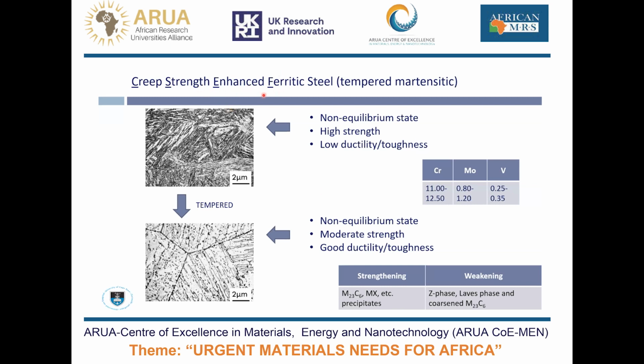So if we take the creep strength enhanced ferritic steel, which is used extensively in steam pipe in a coal-fired power plant, it's deployed in the tempered martensitic condition. And the reason for doing that, of course, is that in the fully martensitic state, it has very high strength, but very low ductility and toughness. So it's then tempered to restore some good ductility and toughness. And of course, moderate strength is key, because strength at the end of the day to sustain the high pressures and high temperature is critically important. But of course, this is still a non-equilibrium state. So although we've taken a highly non-equilibrium martensitic condition, and we moved it somewhat towards equilibrium by tempering it, it's still a non-equilibrium state.